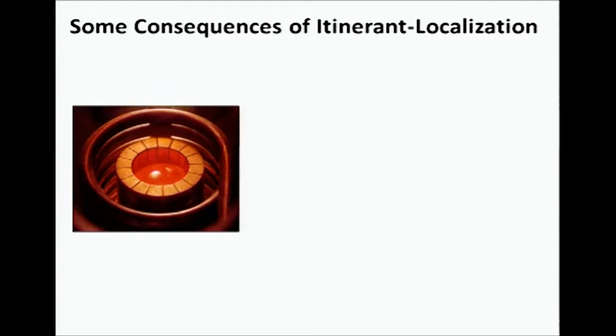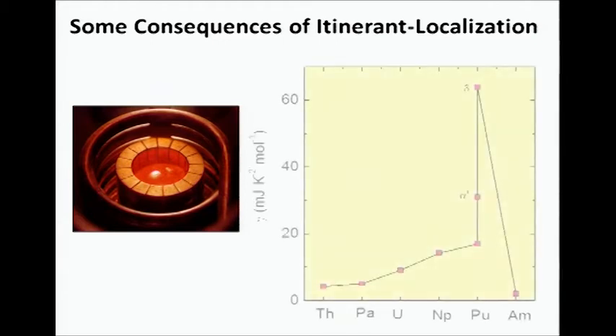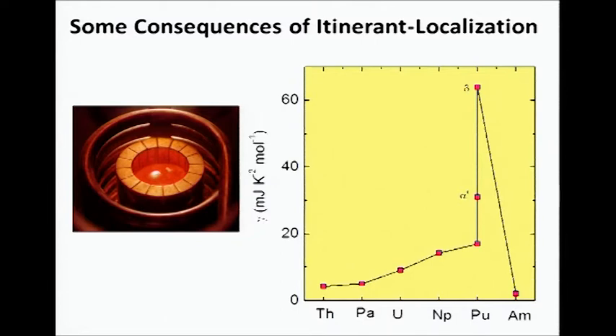This is the way I purified many actinides, and I used some of the samples to look at low temperature specific heat. Jim Smith and I measured some of these - some had already been measured - but this is the electronic specific heat coefficient versus element, and this is just a generalization of what Börje had said. You see localization at americium, and you get all this craziness at plutonium.